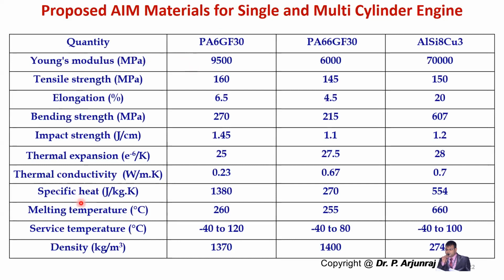And this is a material comparison between PA6 glass fiber 30, PA66 glass fiber 30%, and aluminum silicon copper Cu3 material. You can find that the tensile strength is higher in the case of PA6 with glass fiber 30 when compared to PA66 glass fiber 30, and also the aluminum silicon grade material.